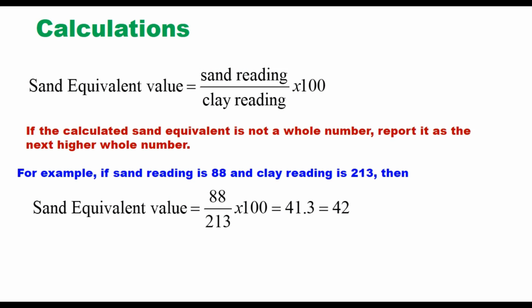Now calculations for sand equivalent value. This is given by this equation: sand reading divided by clay reading multiplied by 100. If the calculated sand equivalent is not a whole number, report it as the next higher whole number. For example, if sand reading is 88 and clay reading is 213, then sand equivalent value will be 88 upon 213 multiplied by 100, that is 41.3, and it should be reported as 42.